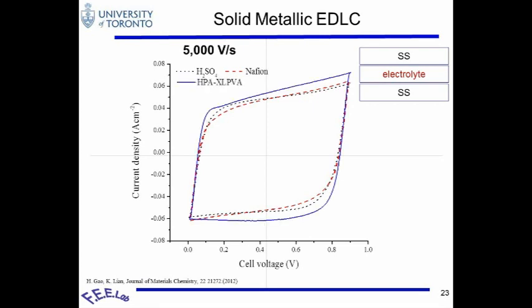The blue one is the polymer electrolyte in the gel situation that you've seen in the previous XRD, in the gel condition. This actually shows even better in terms of resistivity — it's less tilted. If it's more tilted, it means more resistive; less tilted shows slightly more capacitance. So this is from the solid electrolyte, showing that it can reach, and perform equal or better than, the liquid electrolyte or Nafion.